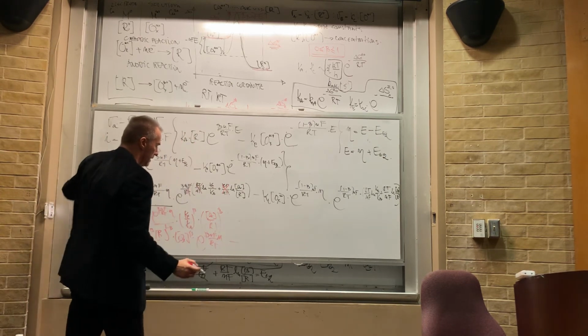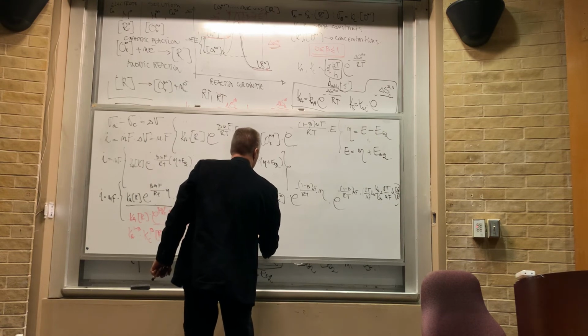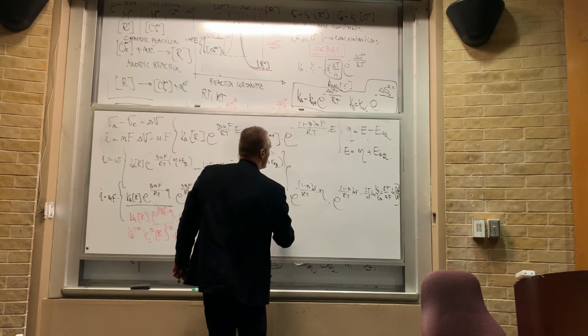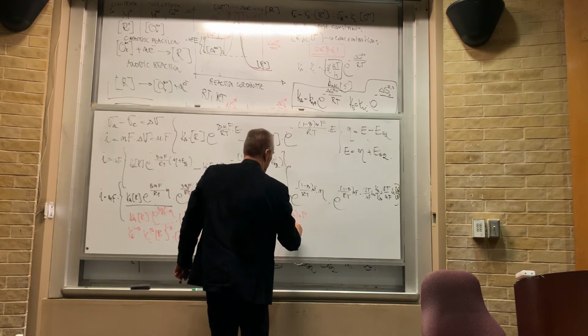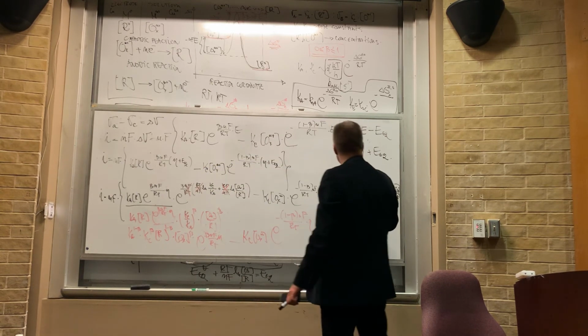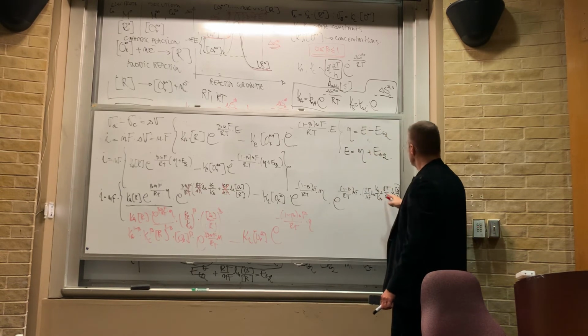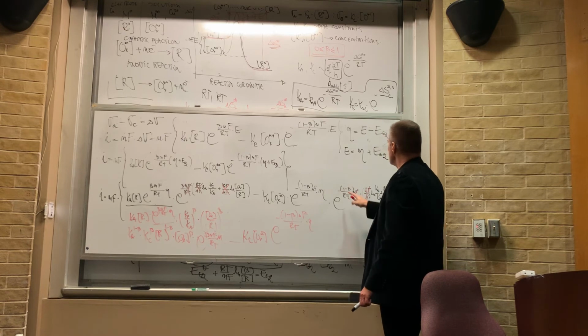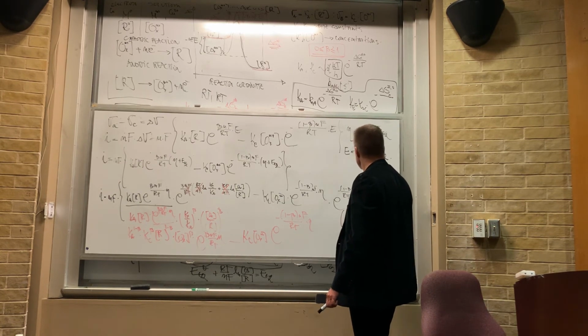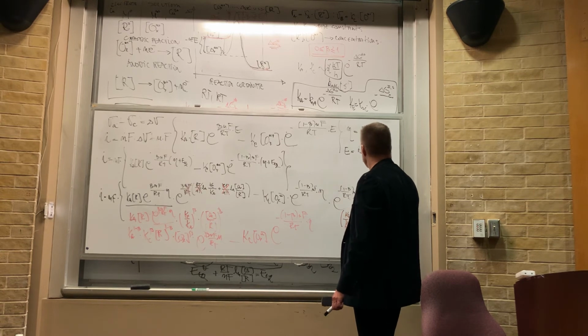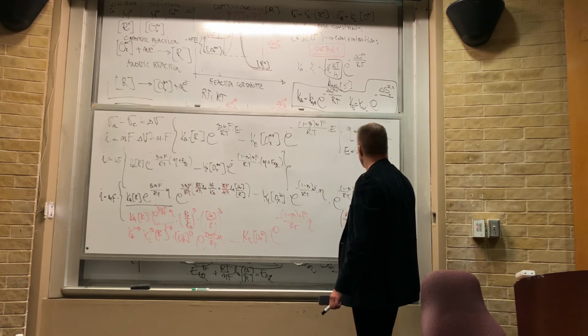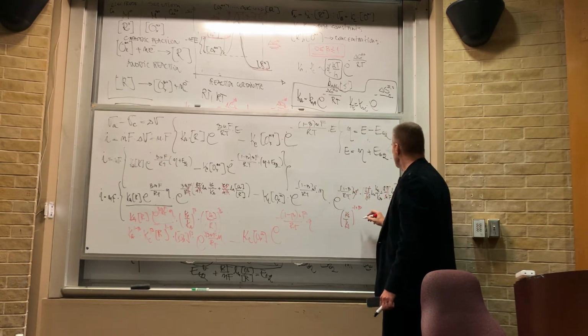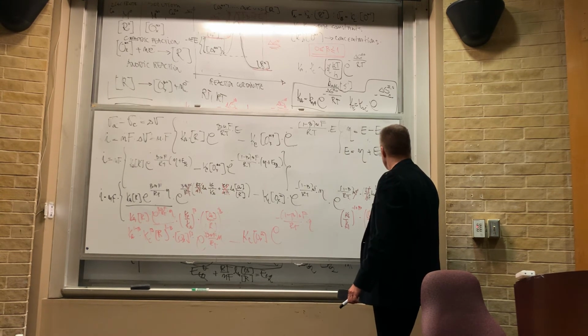Now minus, and we have here Kc, the concentration of the oxygenated species, multiplying this term here, e to the minus 1 minus beta and F over RT times eta, the overpotential, and then the same things apply here. You have nF over RT multiplying RT over nF here, so this conveniently drops. And so what you have really here is minus 1 over beta, and when it goes to Kc over Ka within the logarithm, what you end up with is Kc over Ka to the minus 1 plus beta, right? And then the same thing here, which is the oxygenated species concentration divided by the reduced species concentration to the power minus 1 plus beta.